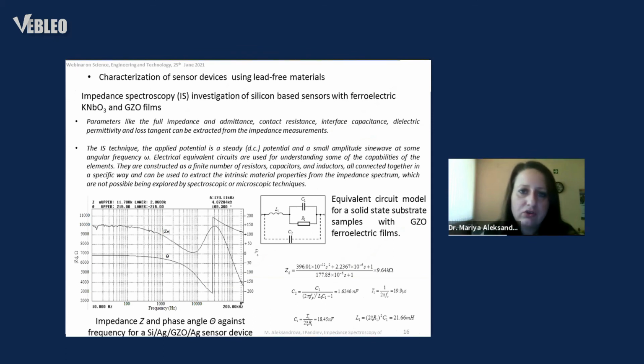We characterized the sensor devices using impedance spectroscopy. It is important to extract the full impedance because it is important to find the impedance matching conditions with signal processing electronics, and in this way we extract some information about the internal resistance and the interface capacitance, which directly affect the time response of the sensor and sampling rate, and some parasitic effects like parasitic capacitors and parasitic inductors from the leads, from the packages, and so on. So these intrinsic material properties could be easily probed by impedance spectroscopy.